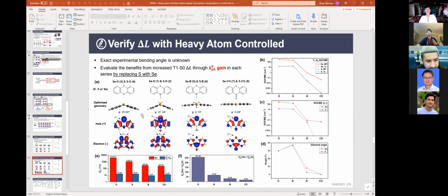But that's not the case. If you look at the spin-orbit coupling here, the oxygen derivative actually has a little bit larger spin-orbit coupling value compared to nitrogen. And we think that's because oxygen is donating more electron density to the total system. Then when you are experiencing spin-orbit coupling, you have more electrons, and certainly you will have a larger spin-orbit coupling value. So we are having something you suggested. That's a very, very good question. We definitely include that discussion in the manuscript, but for the sake of time, I didn't discuss that in much detail.